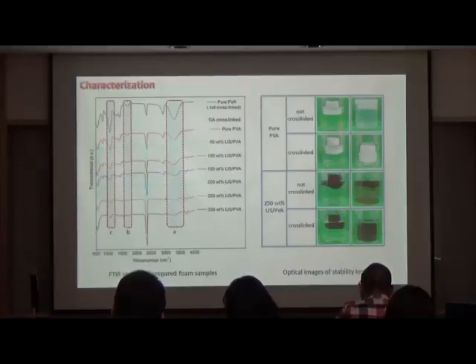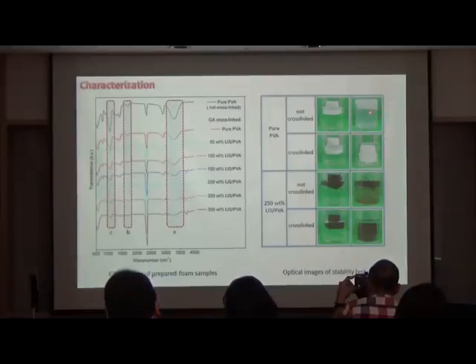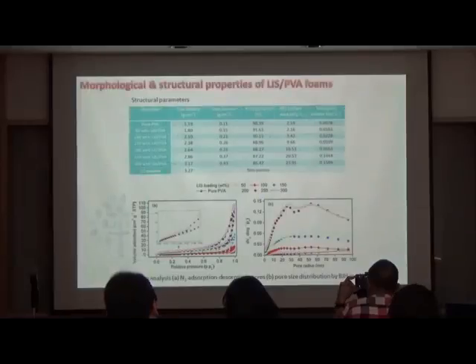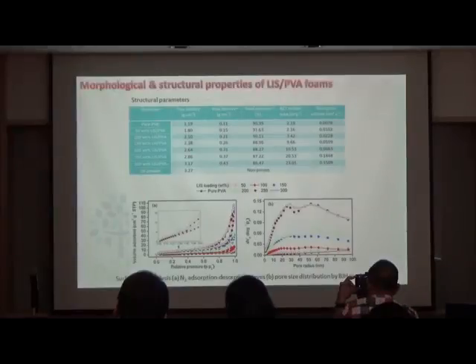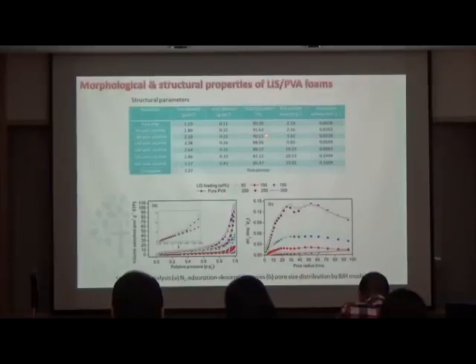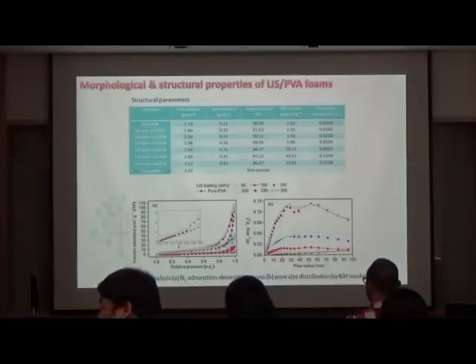Furthermore, the pictures here show the effective preparation of swollen yet aqueous-stable foams, as compared to the uncross-linked composite foams, which readily dissolve in water. Now, the true and bulk density are expectedly increased with more addition of LIS loading, since the LIS adsorbents are denser than the PVA polymer. However, the total porosity decreases with LIS loading, which indicates that there is loss of voids in the composite foams. Now, the opposite porosity trend with the observed surface morphology was further elucidated through surface analysis.